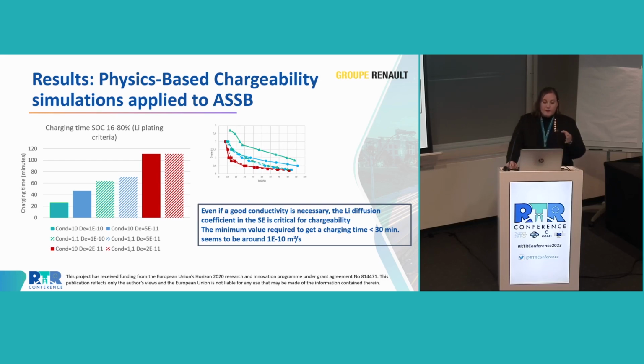tackled the problem of the charging time of the battery. And this was something that, from the research point of view, we weren't aware of. We weren't looking for that. And from that point, we knew that this was something we needed to take into account for the charging time, to reduce it, up to 30 minutes of charging time.